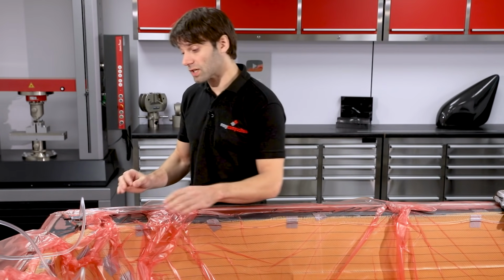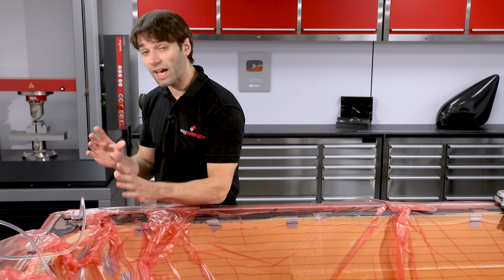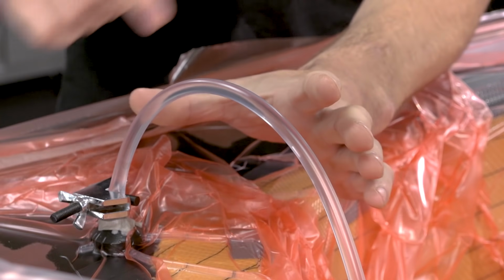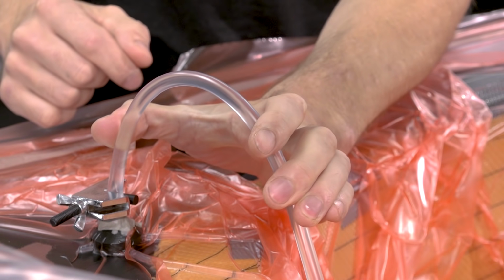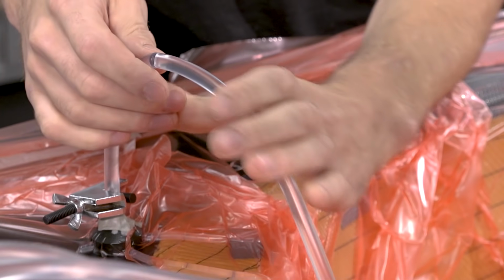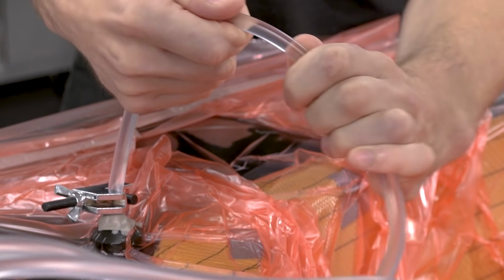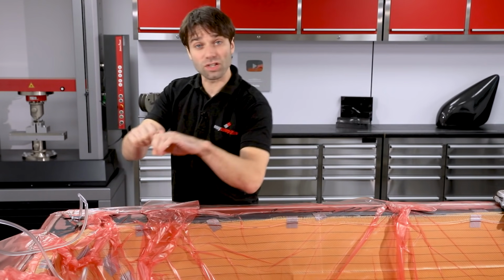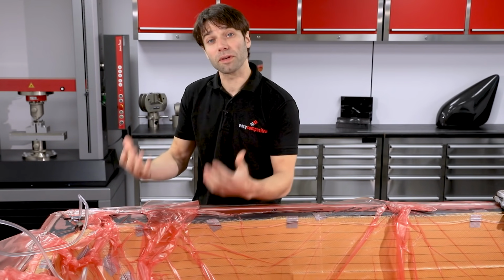A really good indication as to whether the resin is adequately cured for a demould is if you take the resin feed lines full of resin and give them a flex, you should get a clean, crisp crack and break in the resin. If it just flexes, that means your resin is probably not cured far enough, so you might want to leave it a bit longer.